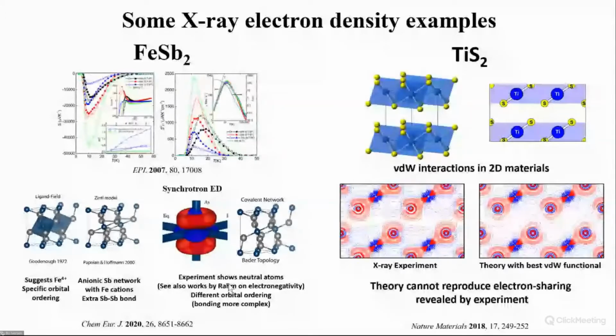Another example of these inorganic solids is titanium disulfide, a typical example of these van der Waals 2D materials, like graphene or molybdenum disulfide. Here you have titanium disulfide, which was the very first lithium-ion battery. And here you have the van der Waals layer gap, and of course the gap determines a lot of the properties, like the band gap. So a question is, what's the chemical bonding across a van der Waals gap?